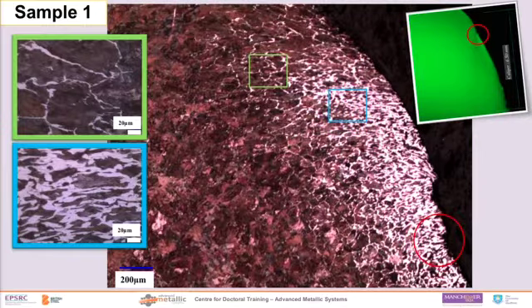This is something slightly different. So this is decarburization on the gauge corner of this sample. The interest in this is because if I can work out what kind of parameters would be necessary to create this level of decarb, it'll give an idea of what kind of environment the rail was suffering at the time of most of this damage being caused.